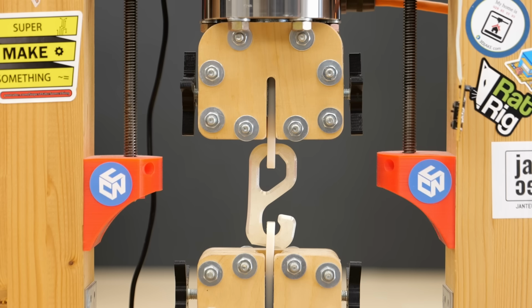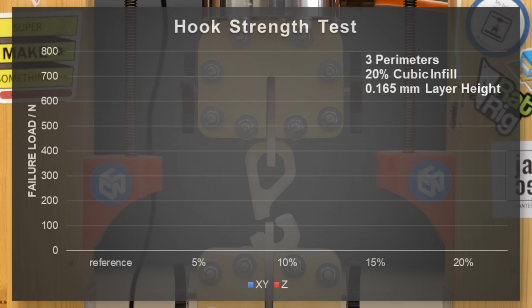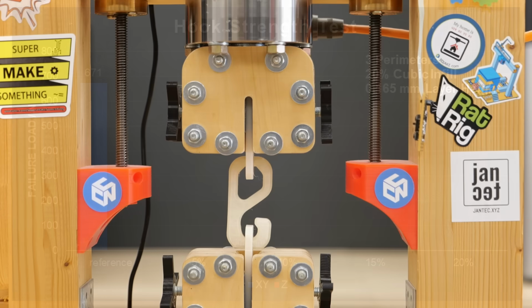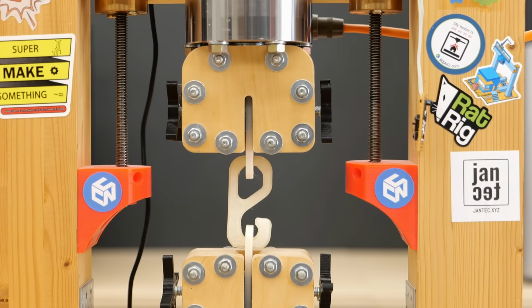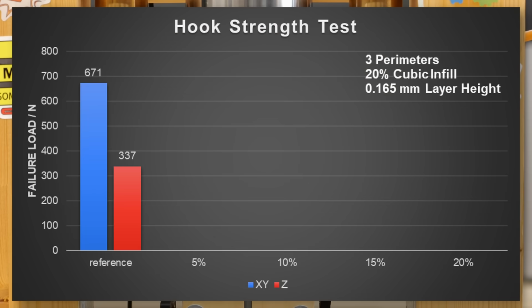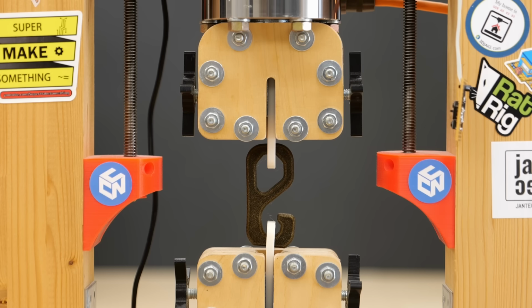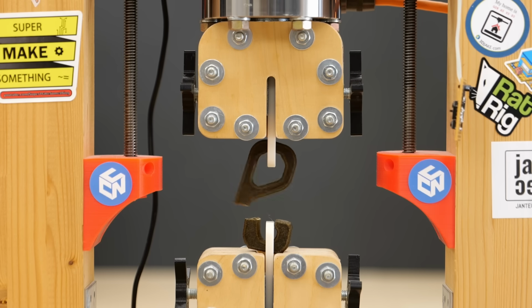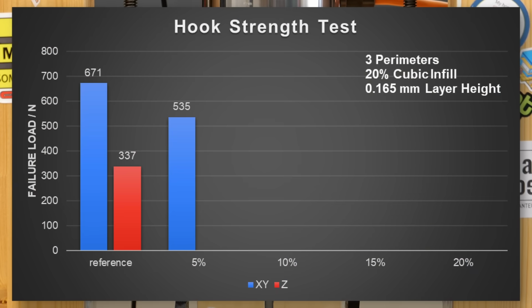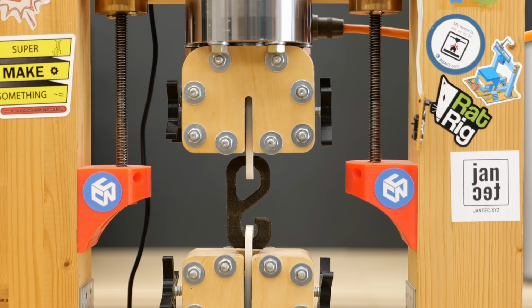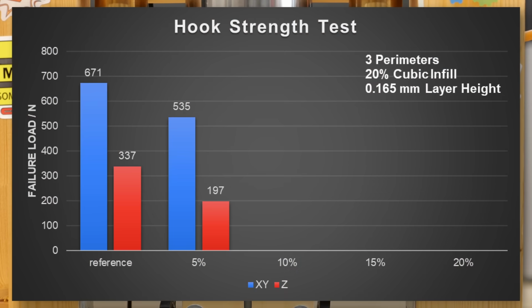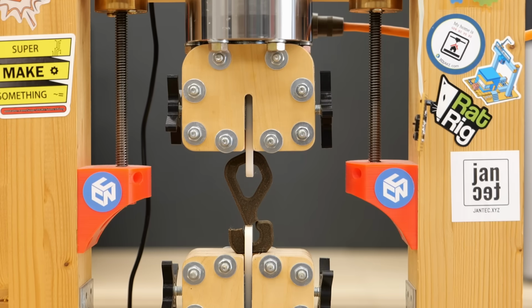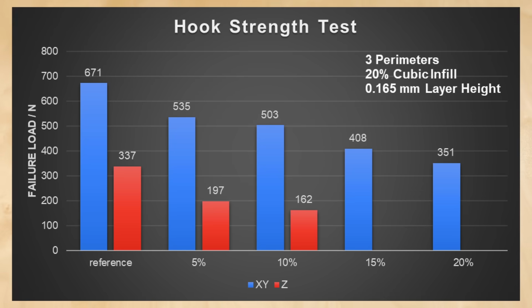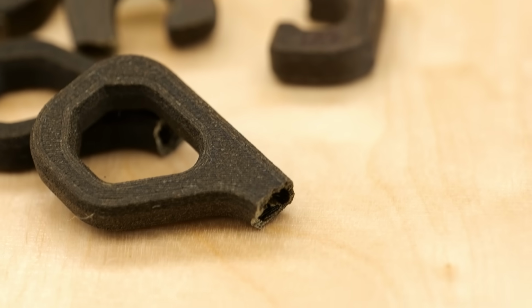Let's start with the reference, where the hook that was printed flat failed at 671 newtons and the standing one printed at 337 newtons, which is a layer adhesion ratio of 50%, which is on the low side for PLA, but acceptable. The horizontal hook with 5% cow dung failed at 535 newtons, which is only 80% of the reference, and the layer adhesion also dropped to 37%. This trend continued for the other hooks, ending with the 20% filled one failing at only half the strength of the reference. You could argue that putting cow dung into 3D printing filament unfortunately doesn't improve the strength of your parts, at least at the particle size and ratios that I use.